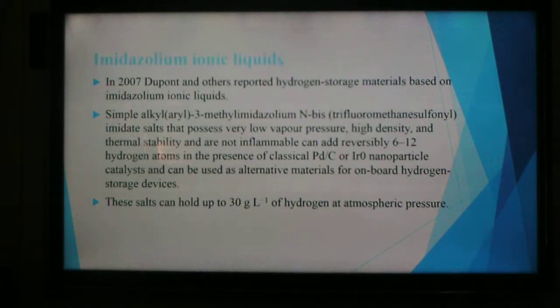Imidazolium ionic liquid. In 2007, Dupont and others reported hydrogen storage materials based on imidazolium ionic liquid. Simple alkyl aryl 3-methyl imidazolium N-bis(trifluoromethane)sulfonyl imide salts that possess very low vapor pressure, high density and thermal stability and are not flammable, can add reversibly 6 to 12 hydrogen atoms in the presence of classical Pd/C or Ir nanoparticles catalyst, and can be used as alternative materials for on-board hydrogen storage. These salts can hold up to 30 grams per liter of hydrogen at atmospheric pressure.